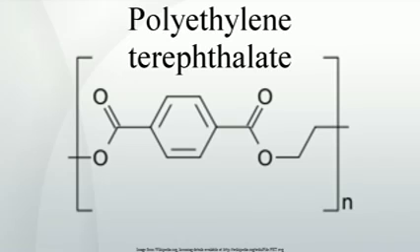The Swiss Federal Office of Public Health concluded that small amounts of antimony migrate from the PET into bottled water, but that the health risk of the resulting low concentrations is negligible, 1% of the tolerable daily intake determined by the WHO. A later, 2006, but more widely publicized study found similar amounts of antimony in water in PET bottles. The WHO has published a risk assessment for antimony in drinking water.